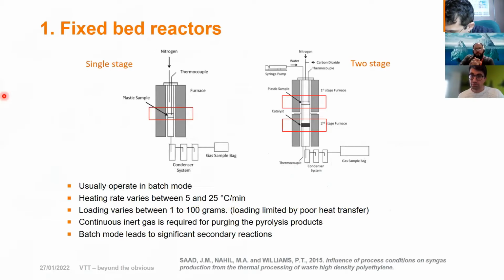What is a fixed bed reactor? Basically, they are very small scale reactors in lab scales. They operate in batch mode, which means the plastic is placed in the reactor on a static bed, because it's a fixed bed. So any inert material here could be sand or something, and then you put your plastic here. You heat it up, and then the pyrolysis vapors are condensed in the condensing system, and the gas is collected in a gas bag. It operates in batch mode, so you cannot put the plastic in continuously.